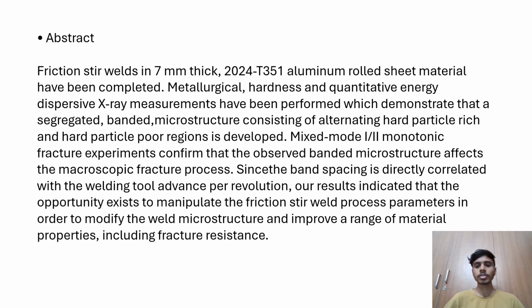Band spacing is directly correlated with the welding tool advance per revolution. Our results indicate that the opportunity exists to manipulate the friction stir weld process parameters in order to modify the weld microstructure and improve a range of material properties including fracture resistance.